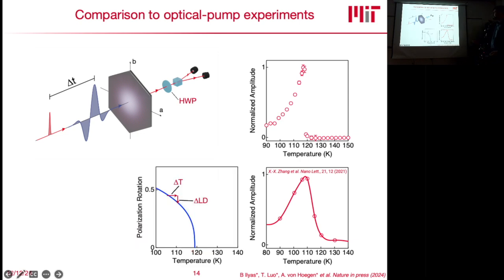And so what this basically does is your laser pulse gives you a very small increase of temperature, delta T. But this then, if you follow this equilibrium curve of the polarization rotation, also translates into a very small change of the polarization rotation. So what you would actually be doing in your transient experiment is sampling the derivative of this curve, if it were a thermal effect. And that's totally what we did.